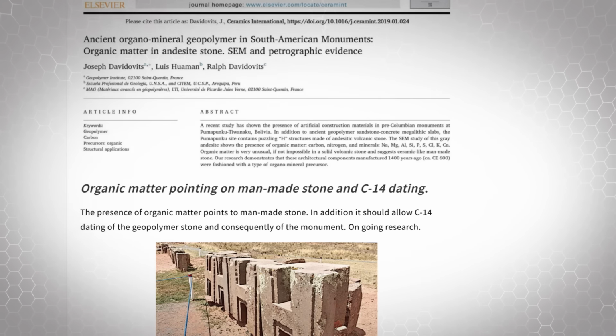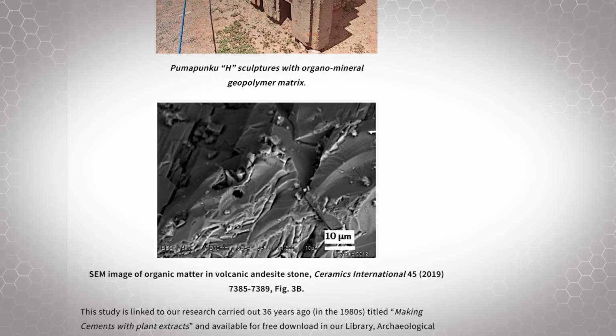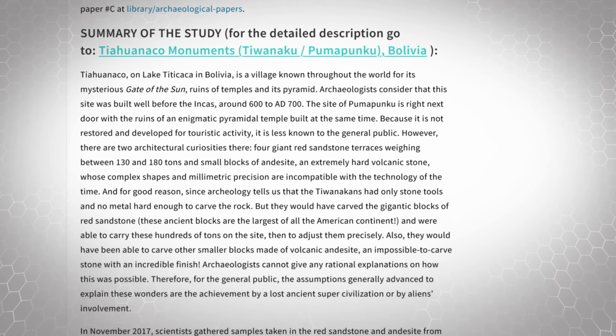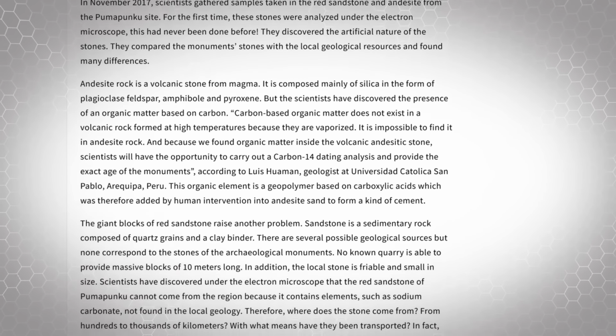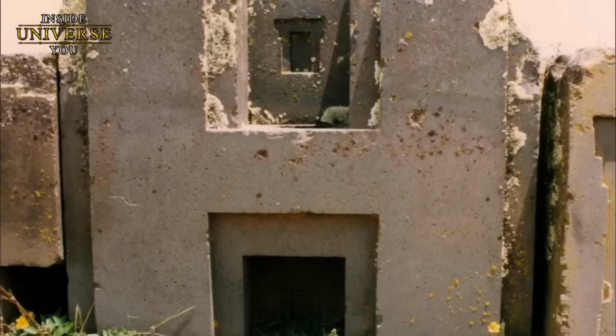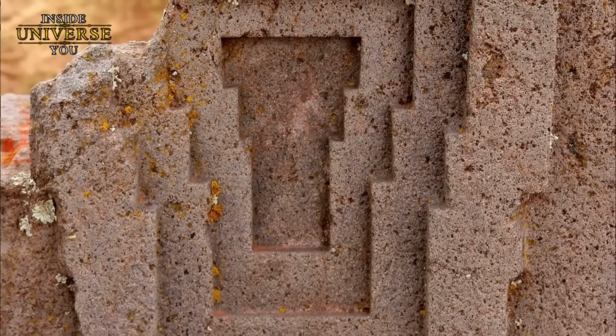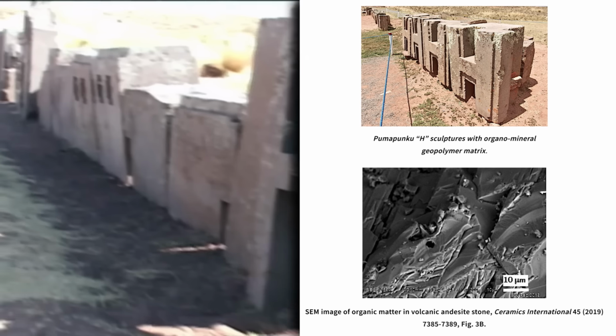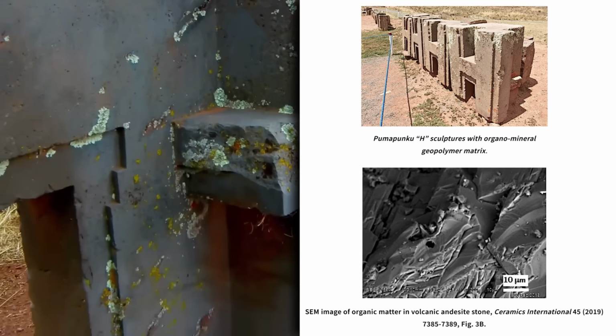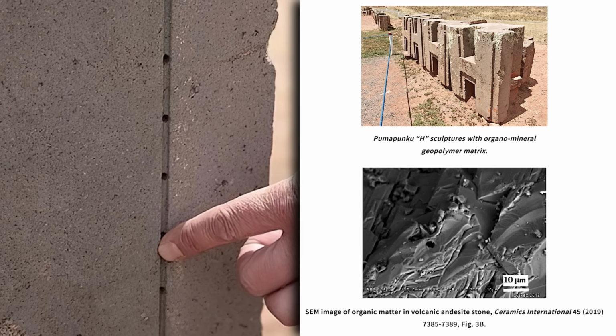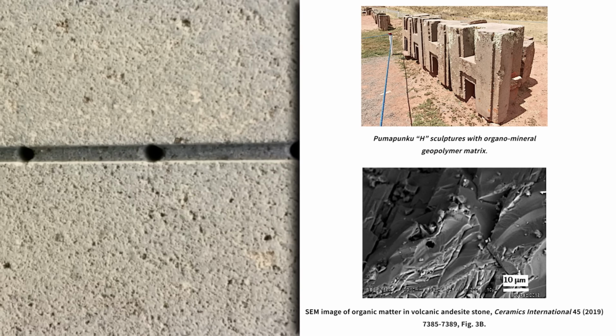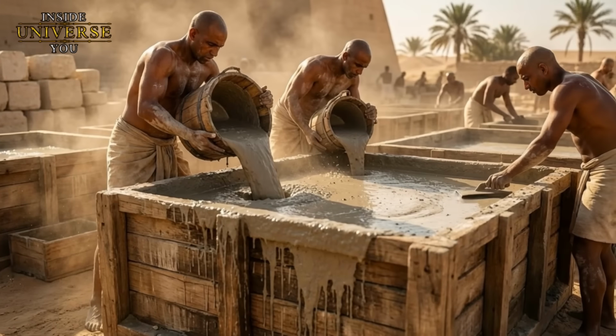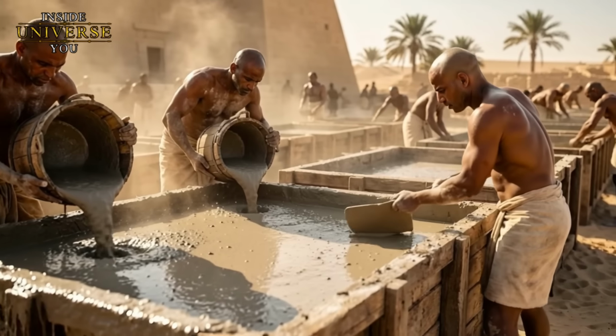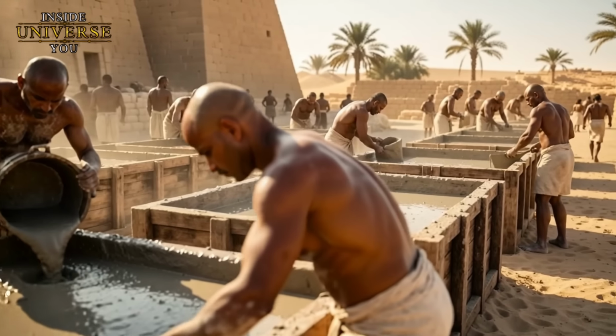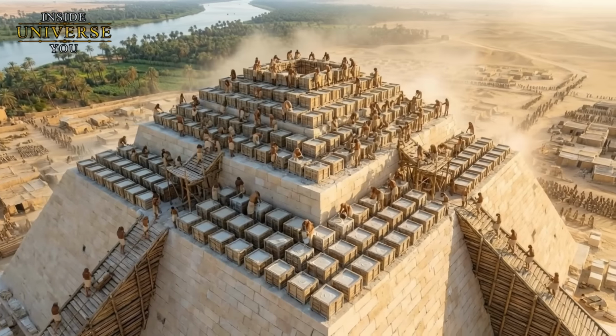This binder showed chemical signatures consistent with aluminosilicate geopolymers, a type of stone-like material created by mixing mineral powders with alkaline solutions. The tests also revealed something even more unusual: the presence of organic compounds inside the stone matrix. Natural volcanic andesite does not contain carbon-based binders, yet some samples showed traces of carbon and nitrogen distributed throughout the material. This suggests that an organic additive, possibly plant-based, was mixed into the stone when it was still in a wet, moldable state. In modern geopolymer research, organic additives are often used to improve workability, slow setting time, or control cracking, making this detail highly significant.